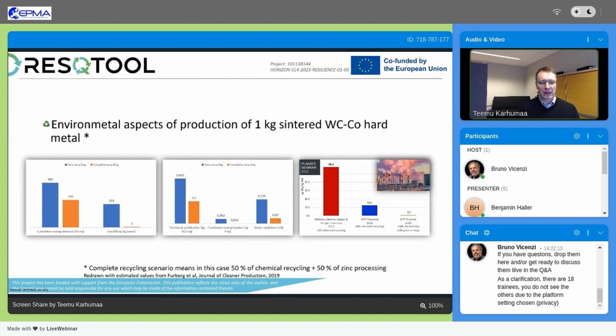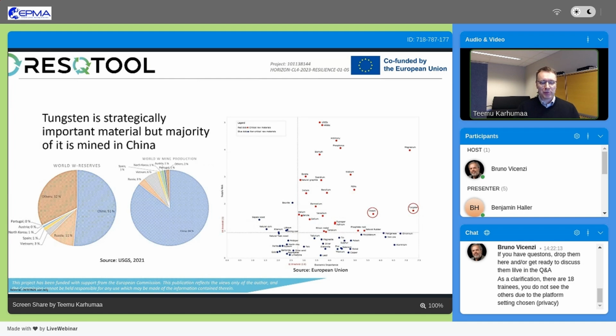with this background. And it's not only the environment that benefits from recycling. Tungsten is a strategic raw material, classified as a critical raw material, both tungsten and cobalt, by the European Union because of the economic importance and because of the supply risk. And the supply risk comes from the fact that most of the tungsten is mined in China, and even more tungsten is produced in China. So there are resources outside of China, but the virgin tungsten is up to 80 to 90% produced in China.